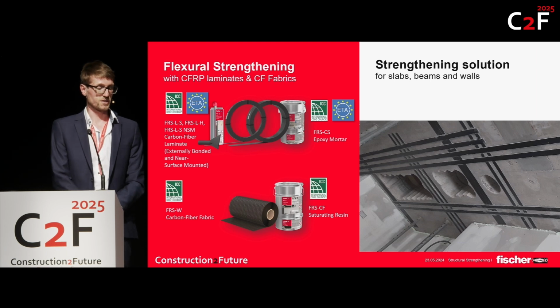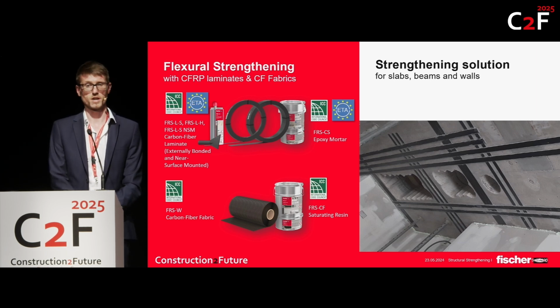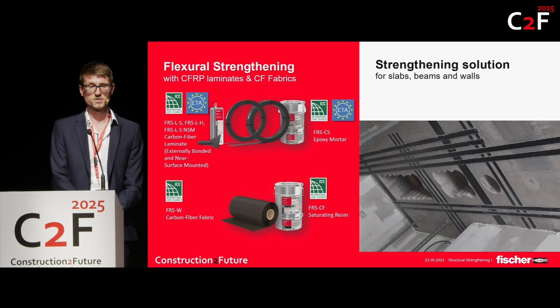And also for the carbon fiber fabrics, we were able to make it with a single resin that can be used for priming the concrete, as well as for impregnating the carbon fiber fabric in the end, which is actually pretty nice. What's not shown here is that we also have an ultra-high strength epoxy-based repair mortar with around 150 megapascal compressive strength.